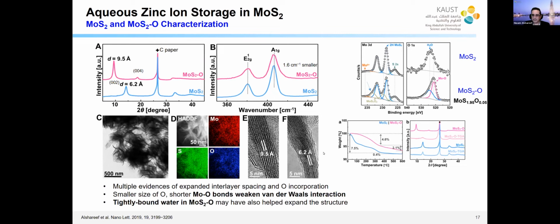So if you do TGA analysis on these two materials, the oxygen substituted molysulfide and the molysulfide, you will see upon heating, look at this is the TGA here, the blue is the molysulfide. The X-ray diffraction pattern hardly shifts for the molysulfide when you lose this water. This is really mostly adsorbed water. But in the case of the oxygen substituted molysulfide, not only would they lose adsorbed water, but there is some water that is lost at higher temperature. We believe this is called the tightly bound water. And you see that after you lose it, with the TGA, you have a shift to higher 2 theta, which means that we actually shrank the material.